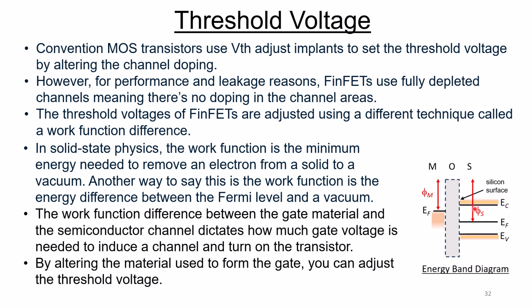The silicon also has a work function, which again is the difference between the Fermi level of the silicon and the vacuum. The difference of these two work functions will dictate the threshold voltage of the device. What they do in FinFETs is they adjust the material used for the metal here to move this Fermi level up and down to adjust the work function difference to get the threshold voltage that you want. This is as opposed to placing more or less dopant in the channel as a conventional MOS device does to adjust the Fermi level of the silicon.